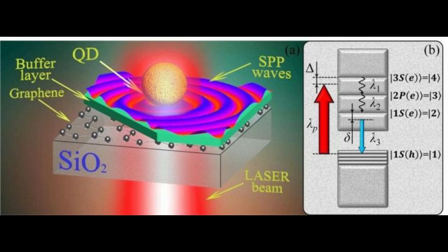Despite the highly efficient energy input into graphene via the quantum dot intermediary, the intensity of the resulting waves is extremely low. Therefore, large numbers of dots have to be used in a specific arrangement above the graphene layer. The researchers had to find precisely the right geometry, the perfect distance between the dots to ensure signal amplification due to the phasing of the near fields of each dot. In their study, the team reports discovering such a geometry and measuring a signal in graphene that was orders of magnitude more powerful than of randomly arranged quantum dots.